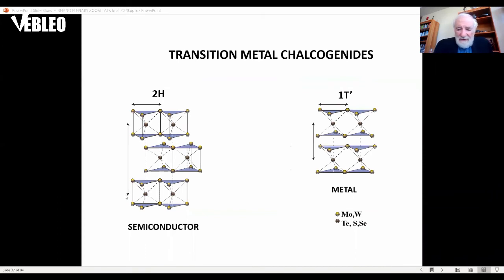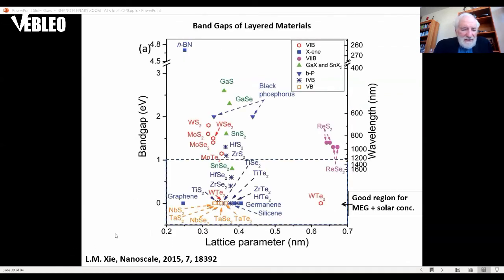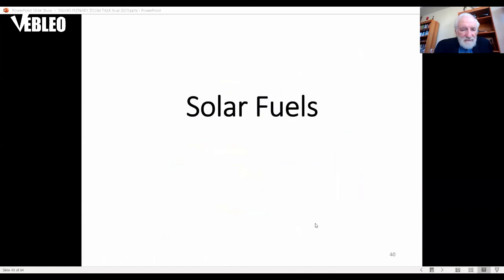Another material that has potential for application are the layered compounds, and they can have band gaps down here, even semi-metals with zero gap. But zirconium ditelluride and titanium ditelluride have band gaps below 1 eV, and so they're all good candidates for this combination of MEG and solar concentration.